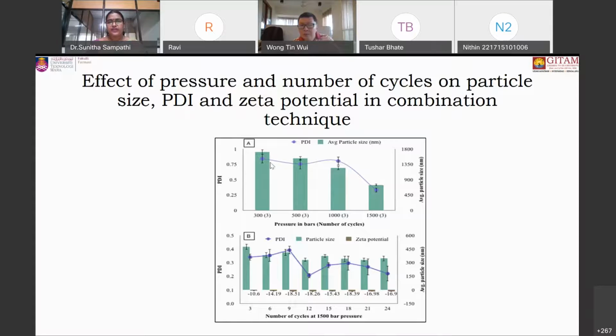And you can see from the graph clearly that when the nanosuspension was prepared at 300 bar, the particle size was around 1400 nanometers. But as the pressure was increased to 1500 bar, the particle size was reduced to near 500 to 600 nanometers. So hence we have fixed the pressure at 1500 bar. And later, at 1500 bar, we continued and increased the number of cycles from 3 to 24. And if you see from the graph, there was a decrease in the particle size at 12 cycles.